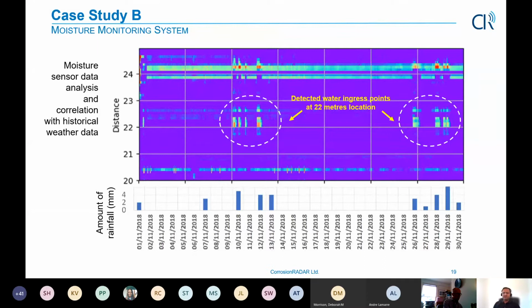Now, there are multiple uses of this. The basic data is about moisture detection and location. So it is a localization tool, for screening, showing that this is where the water is. The second is the periodicity of the water, which is actually another level of risk. If it's periodic, then it's very detrimental to the coatings because chlorides tend to get deposited. The third angle is the prediction.